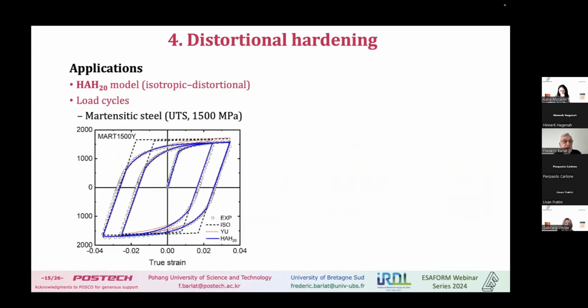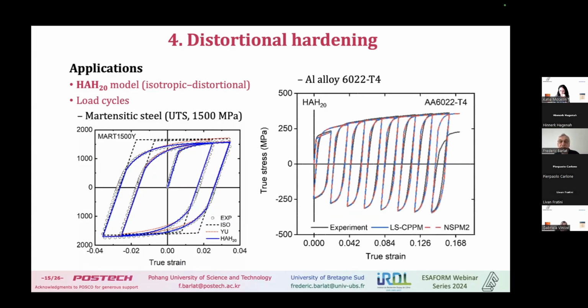We can do cycles also here, and this was done on a martensitic steel with 1500 megapascal of ultimate tensile strength. And again, we have a good agreement here. This is only one curve, okay? Tension, compression, tension, compression, tension. Again, we have a good agreement between the experiments and simulation. And here, this is an aluminum alloy, and this is some kind of cycle plus tension. And the model represents this behavior quite well.